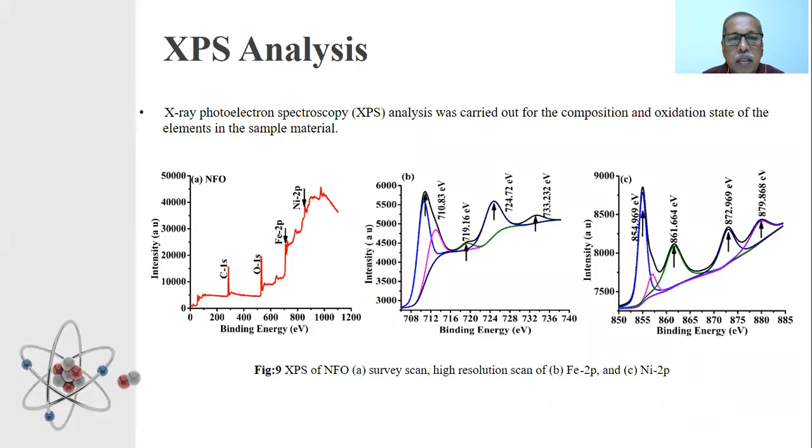XPS analysis were carried out to identify the elements, their composition, and oxidation state. The binding energy peak corresponding to carbon is used as the standard reference. The other binding energy peaks are the expected elements in the composite. After identifying the binding energy peak, high resolution scan in the selected binding energy ranges are taken.